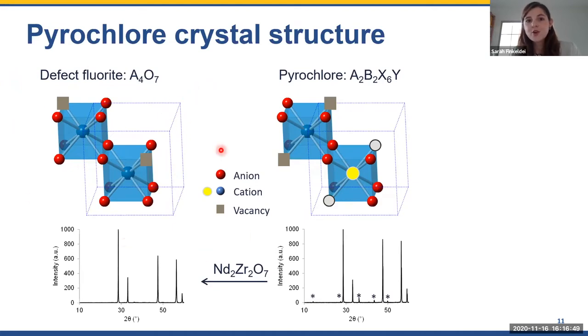But if, in this disordered system, we introduce again a degree of order by fixing these oxygen vacancies at specific lattice sites, what's going to happen is that we end up with a superstructure, with a higher ordering, which is the so-called pyrochlore structure. And due to the fixation of the oxygen vacancies, we end up with two different cationic positions. So we have one cationic position that's eightfold coordinated and another one that's only sixfold coordinated with anions.